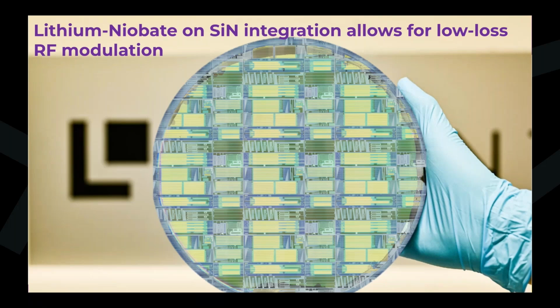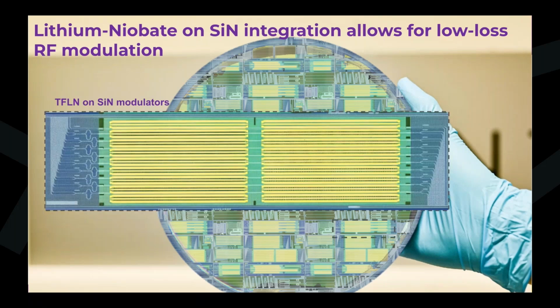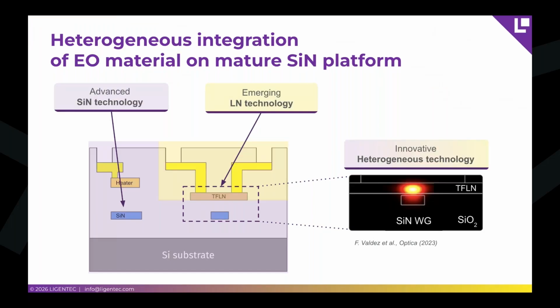So you have here in the blue, you see waveguides, several waveguides. The edge coupling comes from the top. You see waveguides that then have a splitter and that go into several Mach-Zehnder interferometers, and only the straight part with the green is in lithium niobate, and the golden part are the electrodes of the lithium niobate. And afterwards, your edge coupler is going out again from the lower bottom right part of that chip. So we have that heterogeneous integration platform, and that combine a mature silicon nitride platform with electro-optical material.